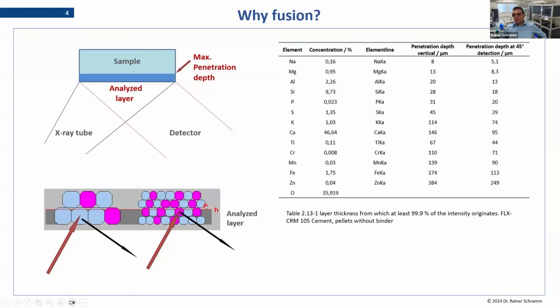And this is what we see when we do press pellets or loose powders: we have quite a high error for the light elements. This is because sometimes the element is lying in the first layer, and sometimes we find it in the second layer, and then it can't be seen by the X-ray. So this all has to do with these particle effects and how deep we measure into our sample. This also means that for these very light elements, we have limitations. The error we get in a loose powder or press pellet is defined by this distribution of particles.